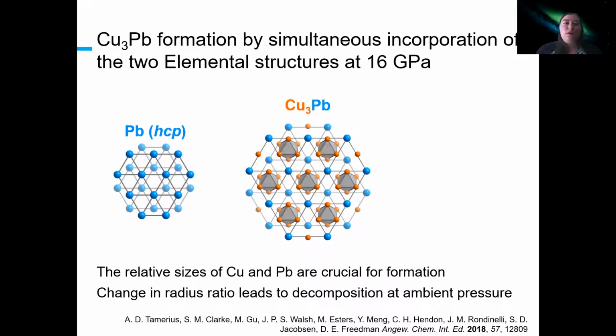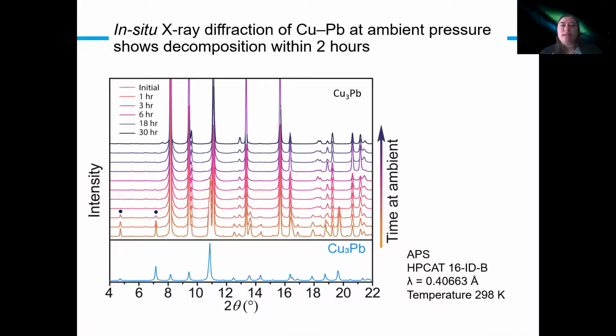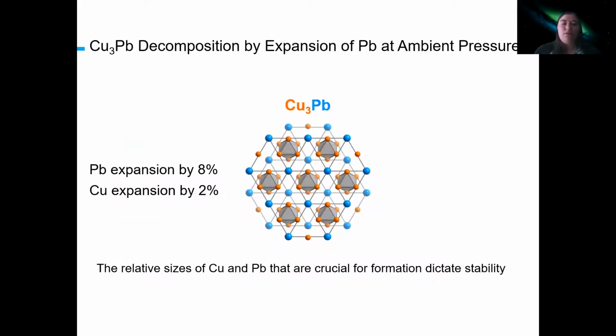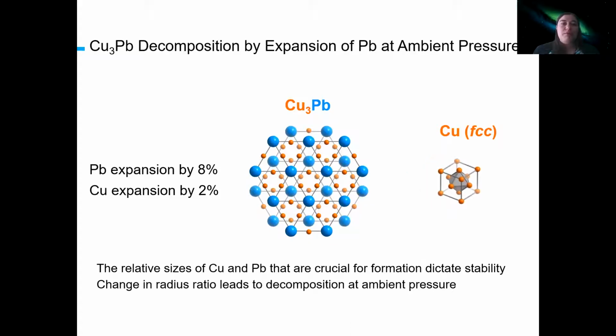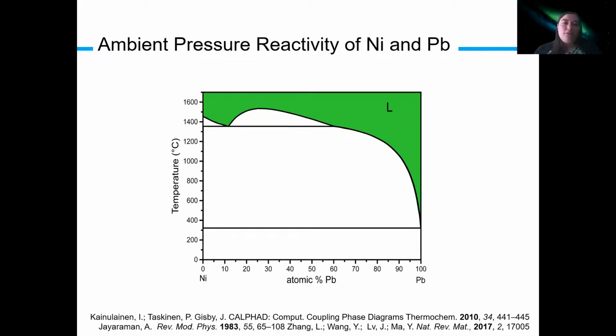And so what we see though is that you have a decomposition of this phase as you decompress. So this phase is almost stable at ambient conditions, but at room temperature over the course of a few hours, it'll start to decompose. And the way I think about this is that you have a big difference in the expansion of these two elements as a function of pressure. So you can imagine that just as we formed this phase by expanding the lead lattice, as the lead lattice then shrinks, you will expel the copper back out of the structure. So I decided to go back to the drawing board and move on to nickel.